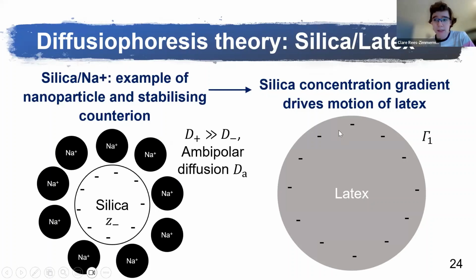In my experimental system, I've got a mixture of silica and latex particles. Now, the silica nanoparticles have a negative surface charge, and they're stabilized by sodium counter ions. The silica nanoparticles are much bigger than their stabilizing counter ions, and so the silica diffuses much slower. We can characterize the diffusion of the silica-sodium pair using the ambipolar diffusion coefficient, D_A. Because of the theory of electrolyte-driven diffusiophoresis discussed on the previous slide, we might be led to expect that the silica concentration gradient could drive the motion of latex particles with a negative surface charge.